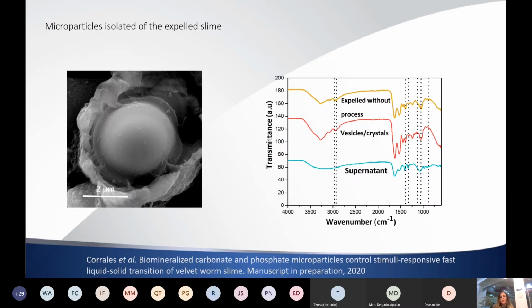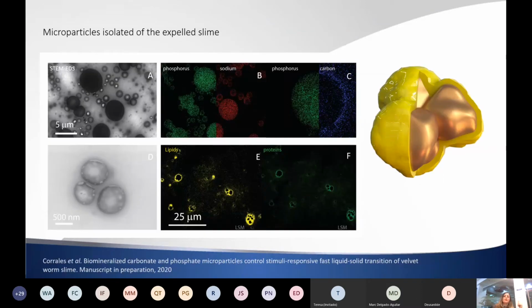So we did the normal analysis: infrared, TEM, EDX. We did a big study, even GCMS, many studies, and we could see that these particles were an inorganic core with an organic shell. And then we could elucidate that these are just kind of vesicles or granules that the animal produces. As you see here, we made a STEM. Why STEM? Because you can do EDX and TEM at the same time.